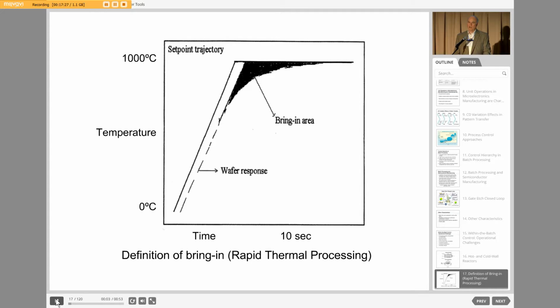So here's an example of what you try to do. If you're going to now take those 200 wafers you used to run all at one time for an hour and a half, now we're going to try to speed it up, because the point is I can't take a long time to run each wafer one at a time. I've got to try to speed it up by running at higher temperature, and so we do what's called rapid thermal processing. And this is something that's familiar to most of you in the room: we have a set point trajectory. We like to be able to follow it. And we have this black area there called the bring-in area that essentially, our goal is to minimize that. So we like to track the set point as closely as possible. You might say, well, why don't you just overshoot it? Well, if you overshoot, then you start damaging the material, and it doesn't turn out to be high quality. So we've got to actually bring it in as fast as possible with as little overshoot as possible.